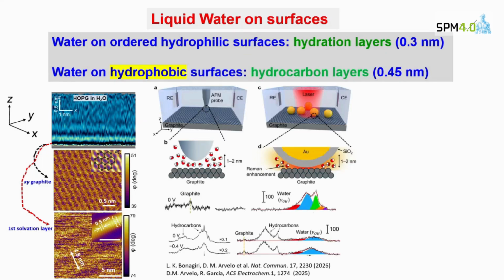So what are those molecules? We have done these studies with molecular dynamics simulations and some specific Raman spectroscopy. So actually, the layering is formed by hydrocarbons. Hydrocarbons, which are in this room here, there are traces of hydrocarbons, very small. You count 1 billion. You count 10 billions of nitrogen molecules in the room.